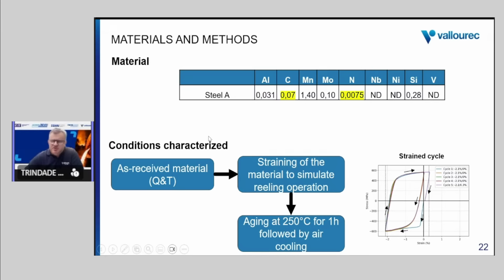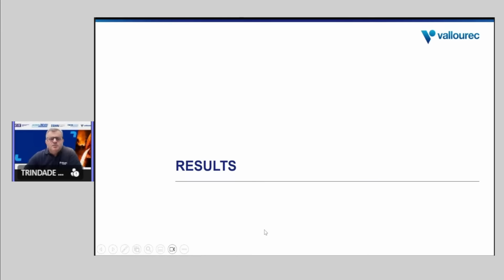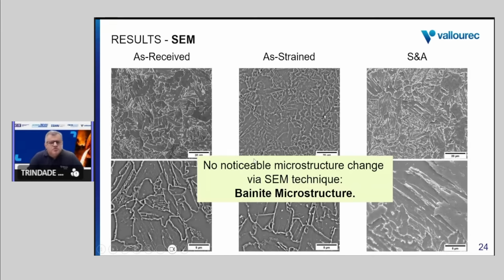What I'm going to show you in the next few minutes is the behavior of this steel in the as-received condition, as quenched and tempered, after straining and after aging at 250 for 1 hour, as recommended by the product standard in the industry. The first finding: we used different techniques to study this material, SEM for example. We could not see any change in the microstructure when we compare all three conditions. The final microstructure after heat treatment of such a low carbon steel is bainite, and this bainite microstructure remains as strained and strain-aged. There is no significant change in the microstructure.